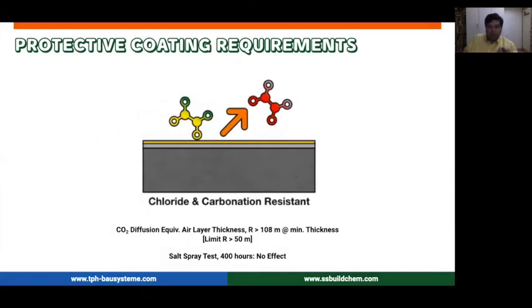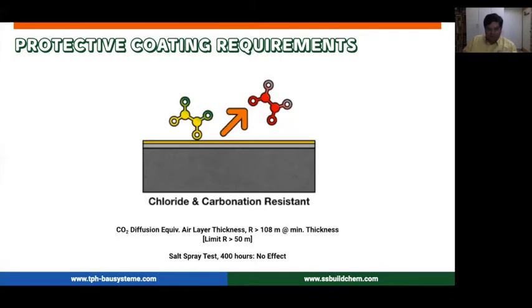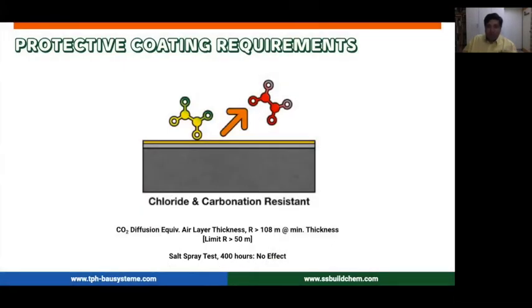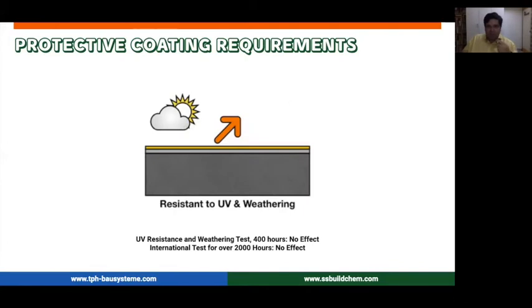Talking a little bit about the requirements, one of the first things is chloride and carbonation resistance. This is tested by testing the carbon dioxide as well as chloride diffusion through your concrete. There are limits to it based on IRC SP80, one of the few Indian codes that you have on repairs. Of course, it's for bridges, but it can be used for quite a lot of different things. It is also tested for salt spray. If you want to use the same coating in and around marine conditions, it should be able to withstand those conditions. So the salt spray test is also important.